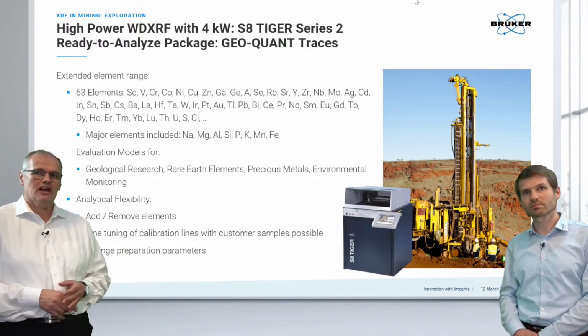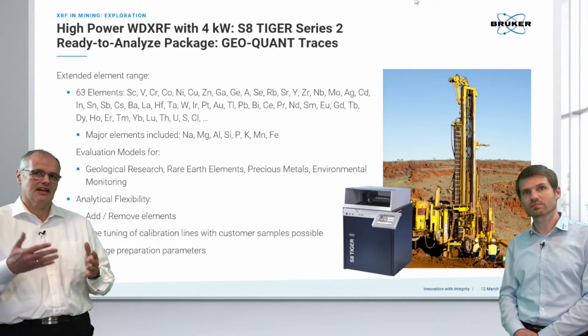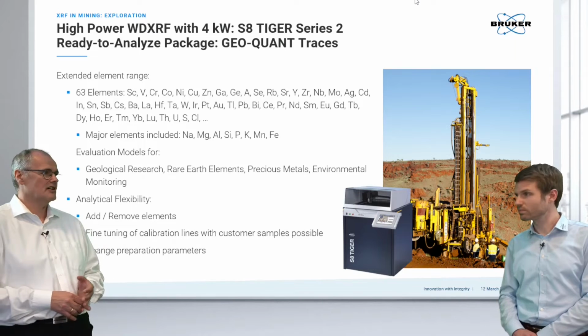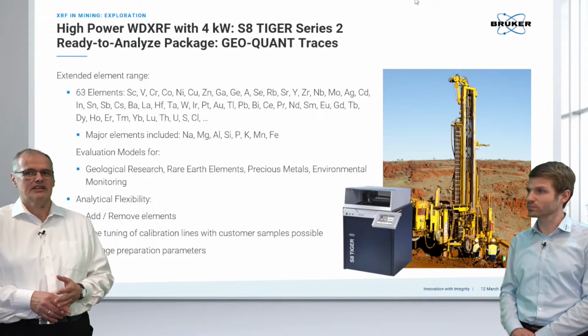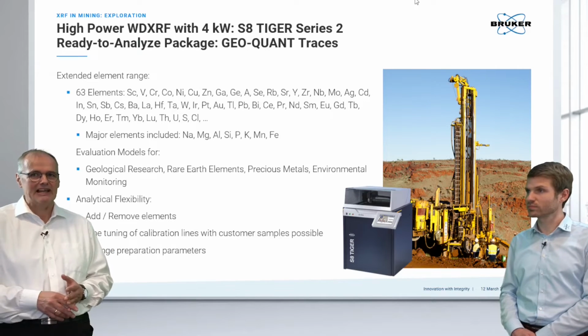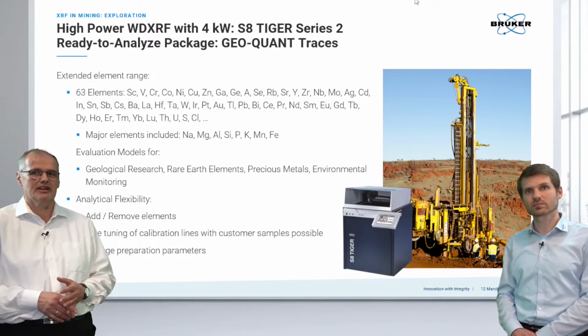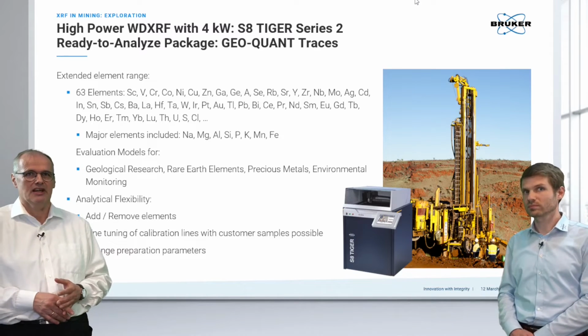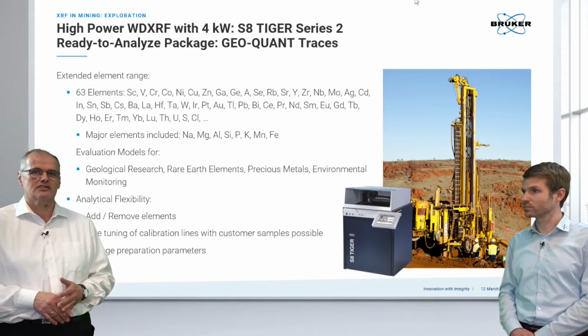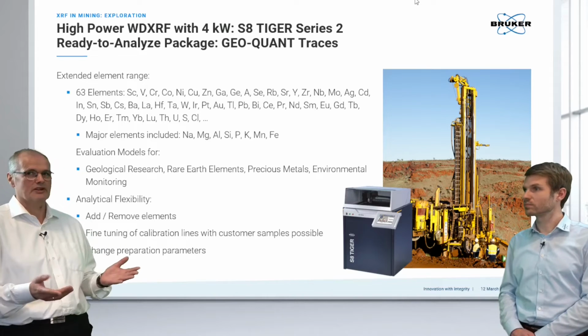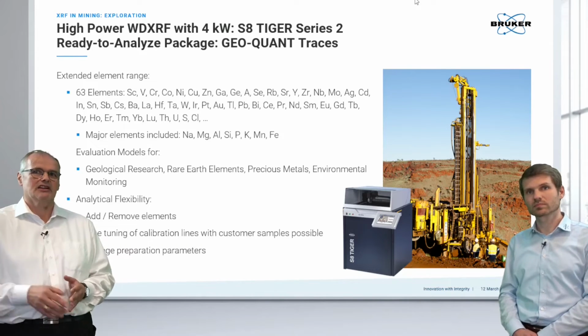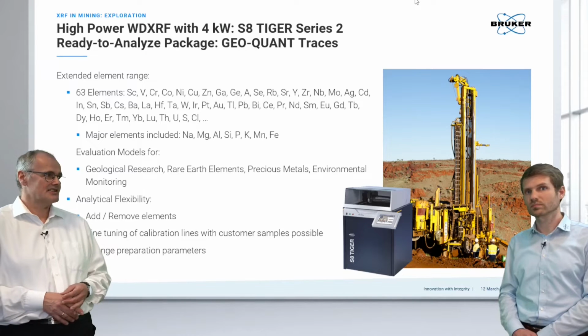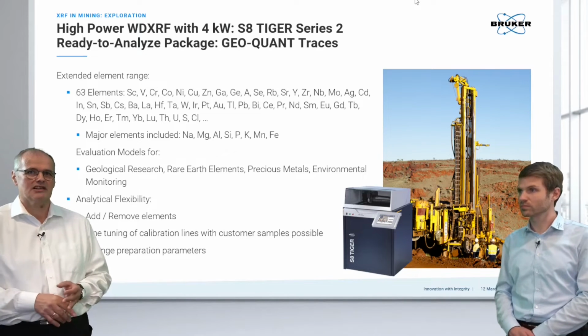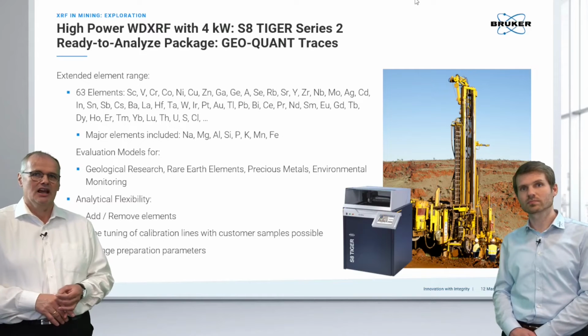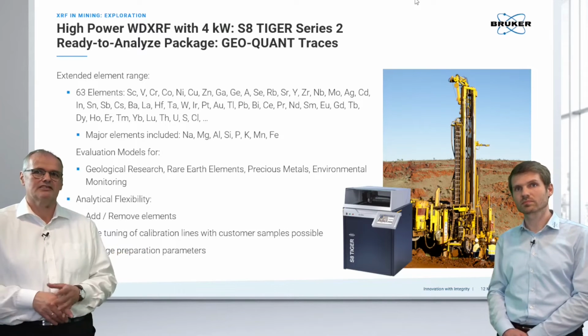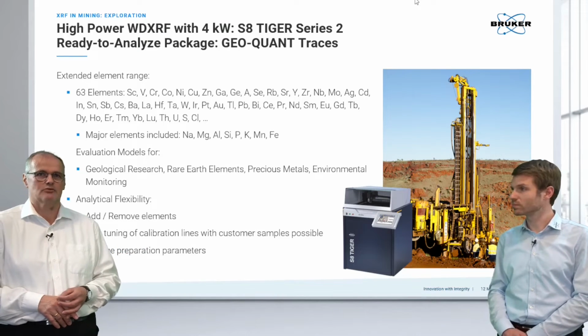As I told you, we have an instrument, and the nice thing in XRF is we can basically standardize an application and put calibration in place once when we set up the instrument and then run it over the lifetime of the instrument. And this we also can do in the factory. So we have come up with a package called GeoQuant Traces. And that's actually a method covering more than 60 elements, more than 50 trace elements and major elements. And actually this is a perfect package for mineral exploration work.